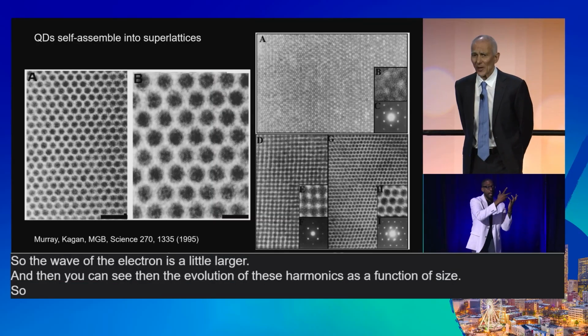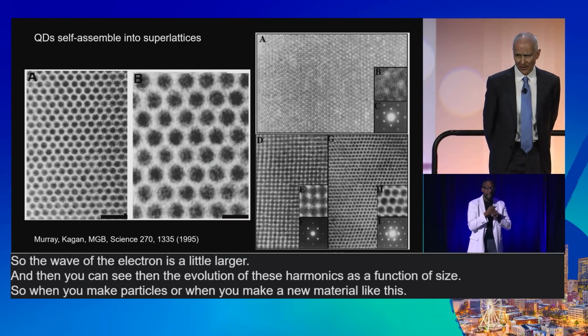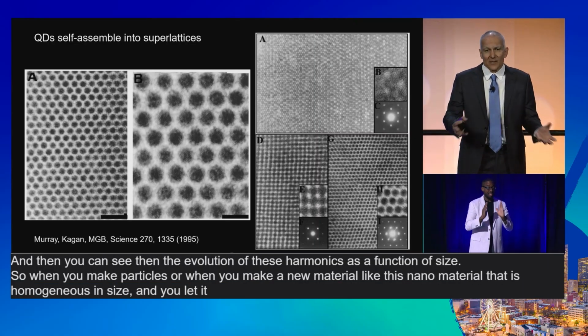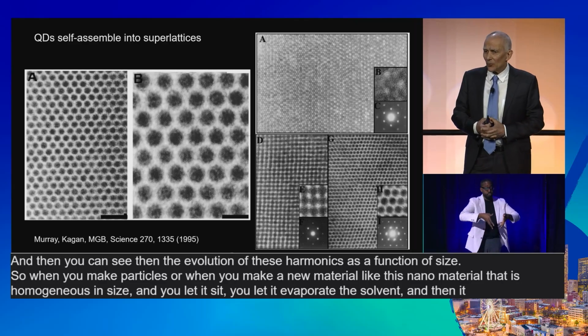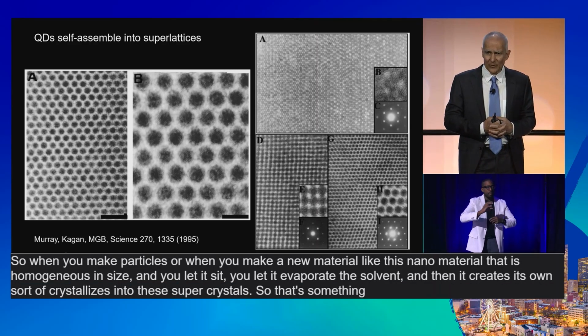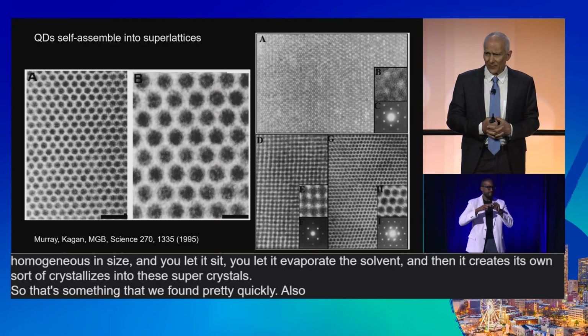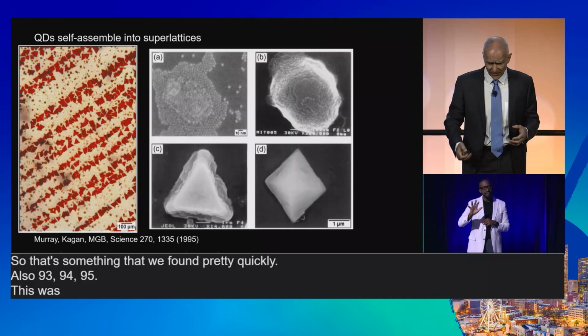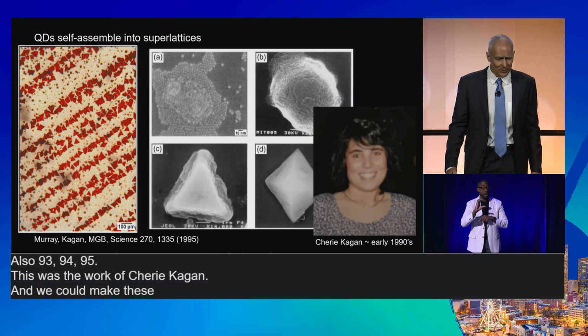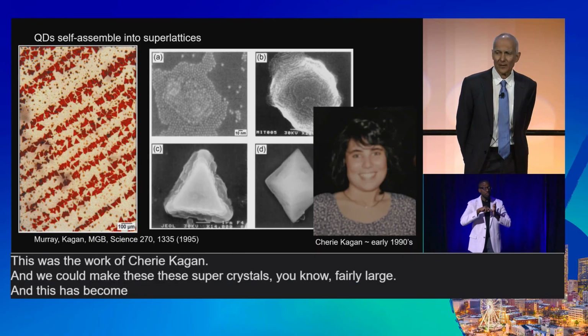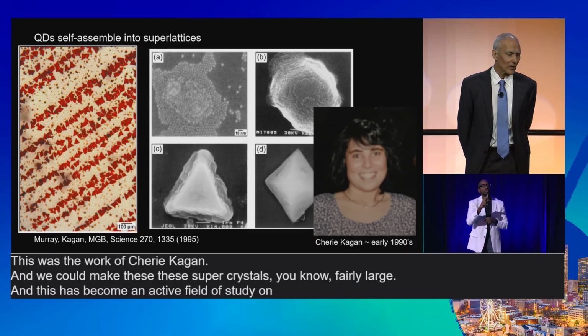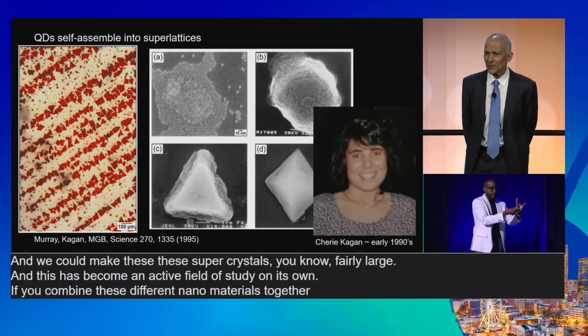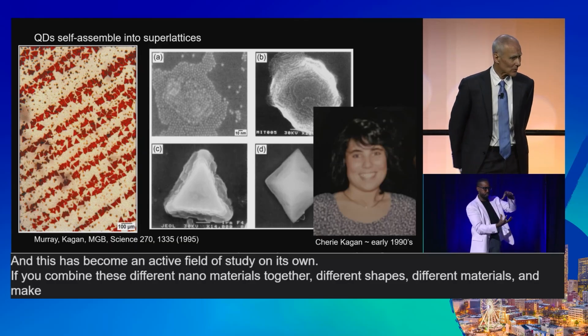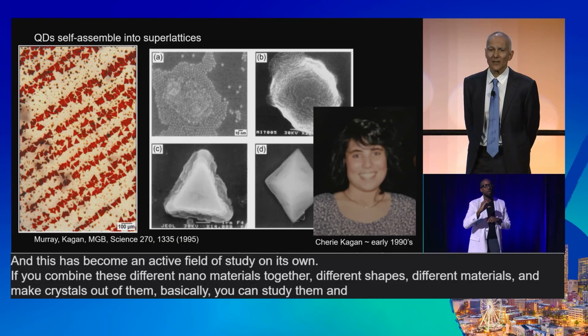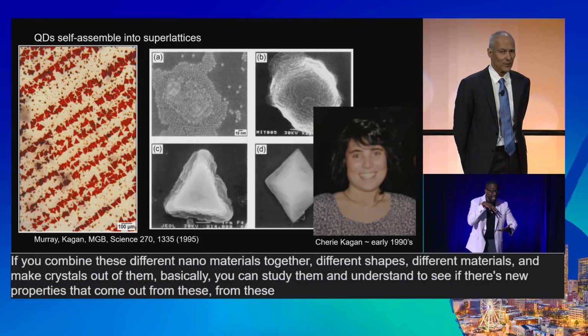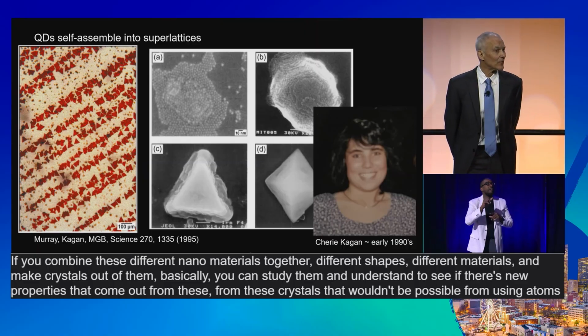So when you make a new nanomaterial like this that is homogeneous in size, and you let the solvent evaporate, it sort of crystallizes into these supercrystals. That's something that we found pretty quickly also, '93, '94, '95. This was the work of Cherie Kagan, and we could make these supercrystals fairly large. And this has become an active field of study on its own. If you combine these different nanomaterials together, different shapes, different materials, and make crystals out of them, you can study them and see if there are new properties that come out from these crystals that wouldn't be possible from using atoms. This idea of a new periodic table.